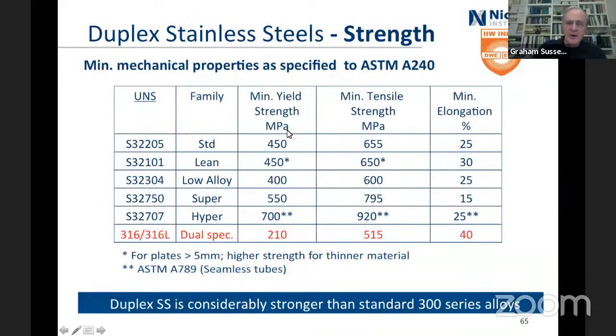Strengths, righto, so compare it with 316, this is a dual spec, and 515 minimum tensile, minimum elongation 40. And we've got at least double. And then we get up to the low alloy, the super, and the hyper, really, really strong. And the minimum yield strength, this is the thing that's going to determine whether it stretches or not. And this is when it'll break, hopefully not. And the 789 is for this seamless tube.